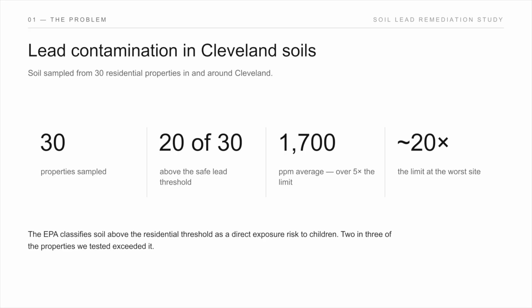But what we did is we started with sampling sites in Cleveland. We took samples from 30 properties. 20 out of the 30 of them were above the lead safe threshold, way above. It had an average of 1,700 parts per million, with the average or the safe level being some say 300, but it's probably more like 200. But we used 300 for this paper, and the worst being actually 20 times that, so about 6,000 parts per million.